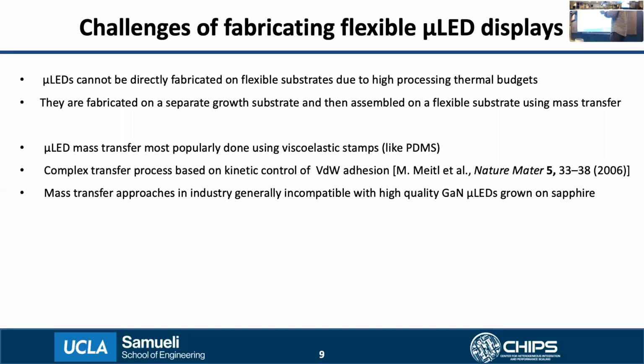However, here is where the problem lies, because micro LED mass transfer that is currently done in both industry and literature is mostly done using techniques such as viscoelastic stamps, like using a PDMS stamp to stick to and pick up the LED using van der Waals adhesion. And these kinds of mass transfer techniques are typically very complex and also have poor yield. They are also not compatible with high quality GaN micro LEDs, which are grown on sapphire substrates, because these kinds of LEDs have to go through a process called laser liftoff to detach them from the growth substrate, which these mass transfer approaches cannot really handle because the forces that hold the devices are weak.